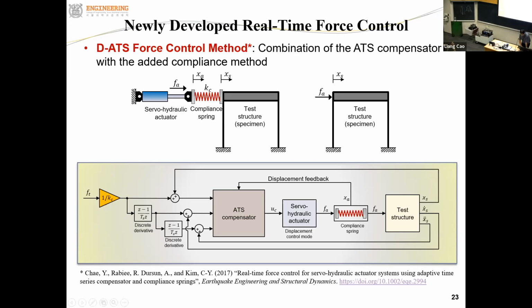We just inserted a spring, a compliance spring or linear spring, between the actuator and test setup. So according to Hooke's law, as long as the spring inserted here behaves linear elastic, then the spring force is proportional to the spring deformation. So if we can control the spring deformation accurately using the actuator here, then we can control the force applied to the test specimen. That's the basic idea here. So by using the ATS compensator and this compliance spring, we are able to achieve good force control.